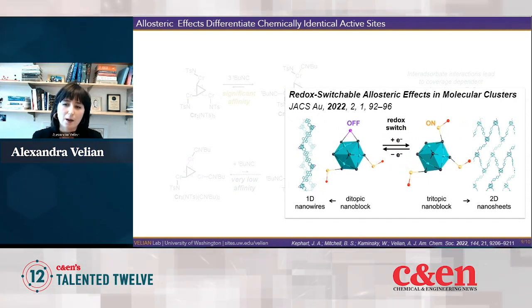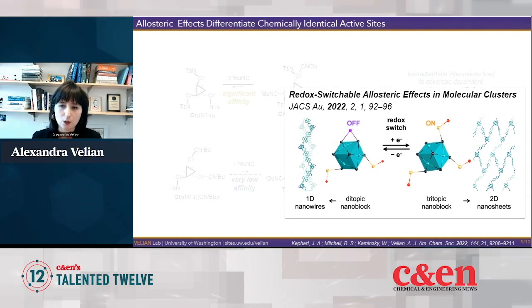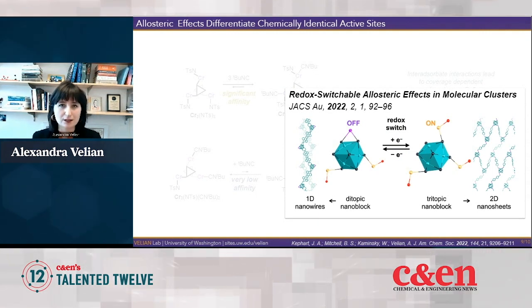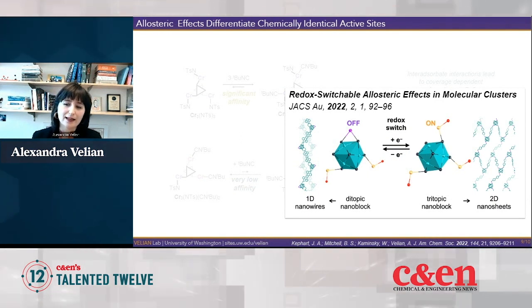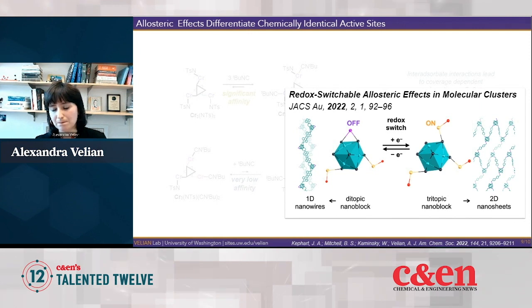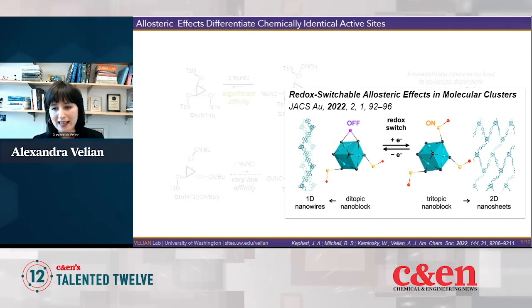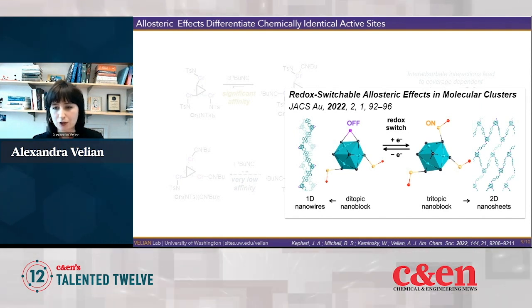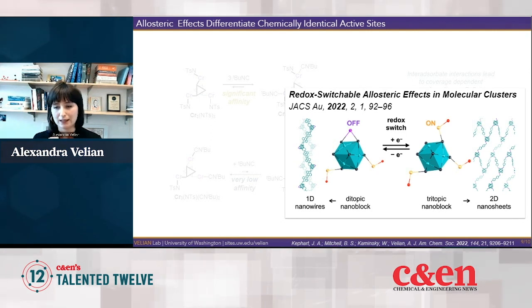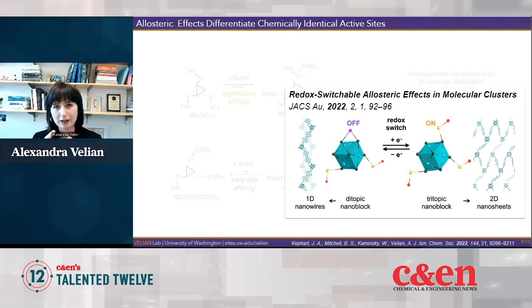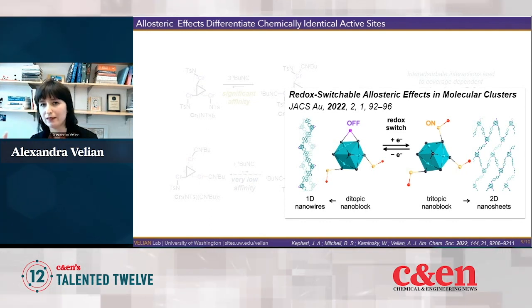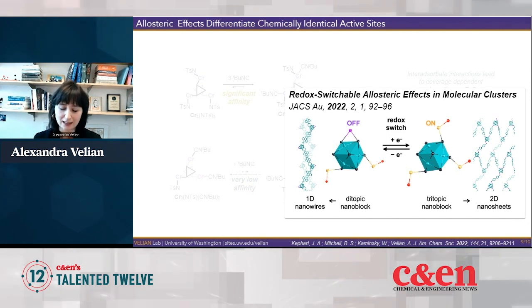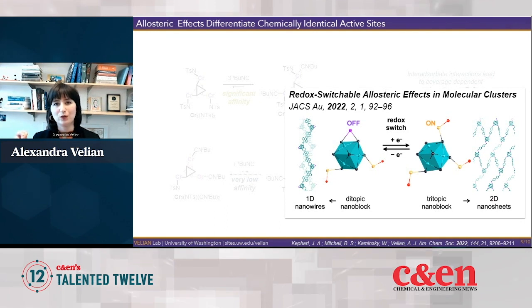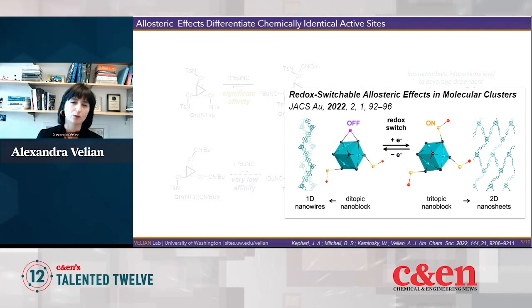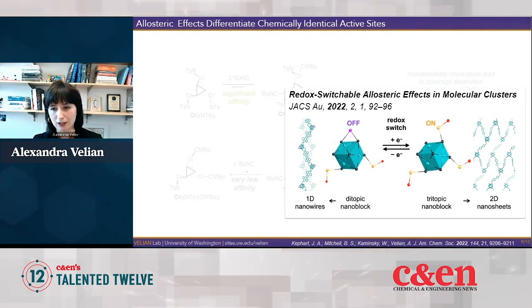seed the synthesis of these programmable or stimuli responsive materials. So the clusters themselves actually are fantastic building blocks for materials, and we are exploring that in the group. But here's a way in which this allostericity enabled us to really use it in material synthesis. So this table of contents graphic illustrates a similar cluster. You can see that cobalt selenide cube in green, but then on the surface, there are three initially chemically identical sites. Now, upon exposing these edge sites, which are zinc in that particular case, to ligands, it turns out that only two of them engage with ligand binding. Again, this information gets transmitted from one edge to another, altering reactivity of the neighboring edge sites.